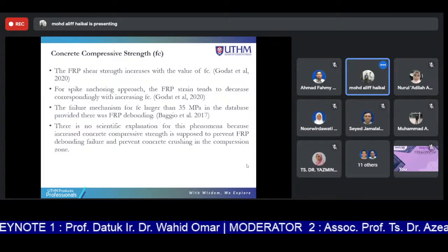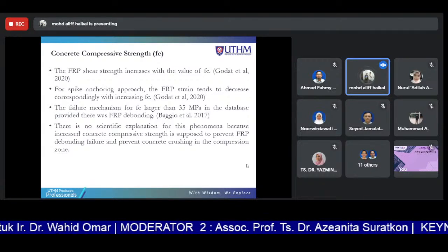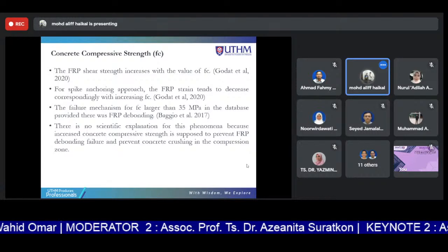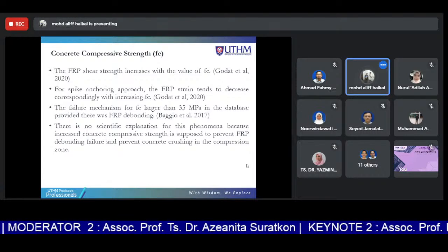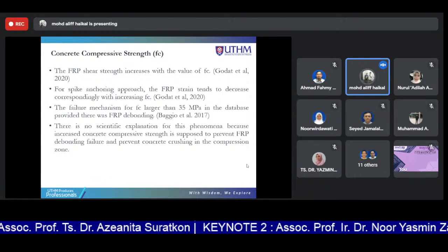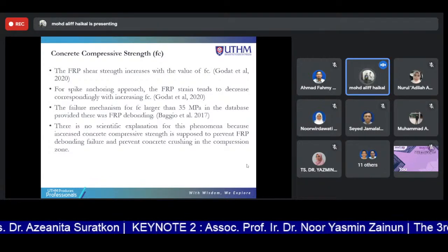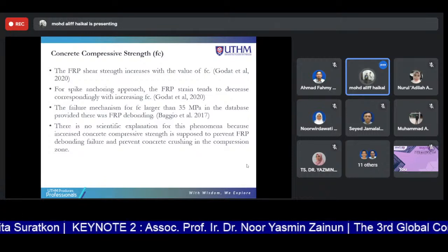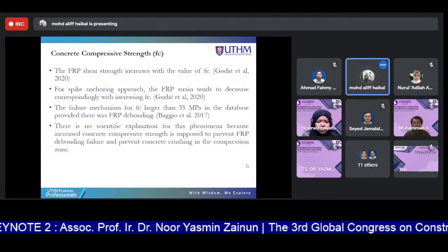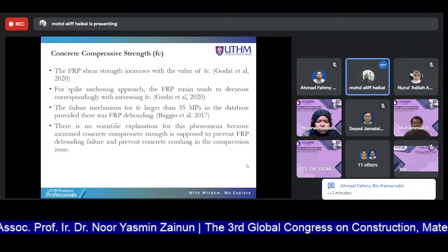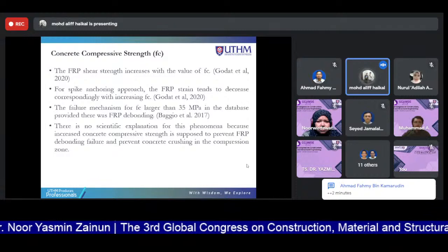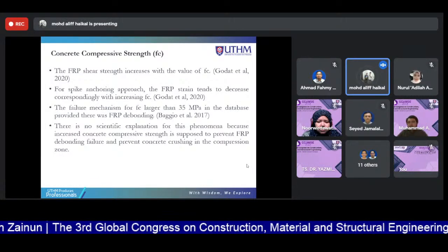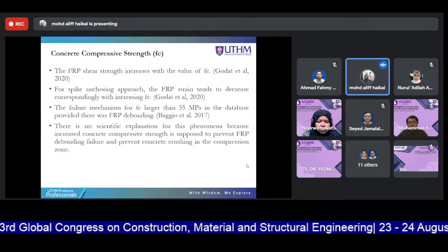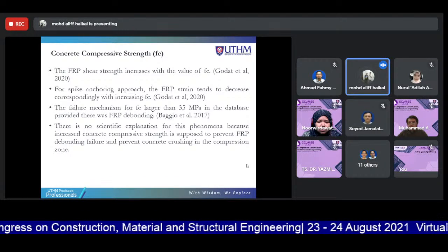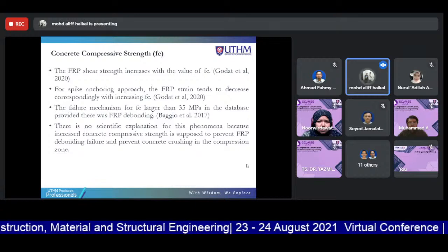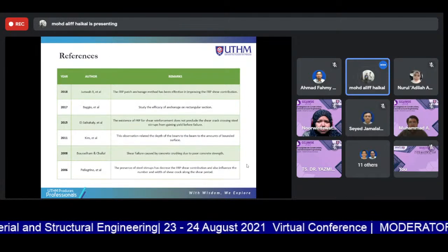And let's go to the concrete compressive strength. The FRP shear strength increases with the value of concrete compressive strength. For the spike anchorage approach, the FRP strain tends to decrease correspondingly with an increase of concrete compressive strength. The failure mechanism for concrete compressive strength larger than 35 megapascals in the database provided was FRP debonding. There is no significant explanation for this phenomenon because increased concrete compressive strength is supposed to prevent FRP debonding failure and prevent concrete crushing in the compressive zone. This is the reference that